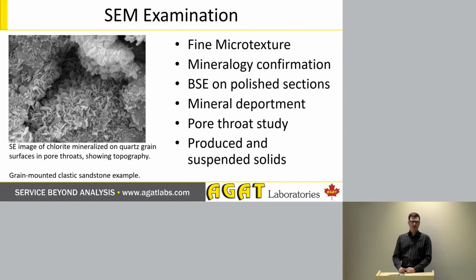For scanning electron microscopy, we're looking at the very fine microtexture. We're zooming in great detail into the rock and actually looking at what's going on inside the pore system itself, zooming in on those pore throats to actually measure their width and see which minerals are present. We can also carry out polished section SEM examination, where we take a similar thin section to the petrography, but we polish the surface very finely. And then we can look at that with a backscatter and see the density difference between minerals, and also look at things like organic matter.